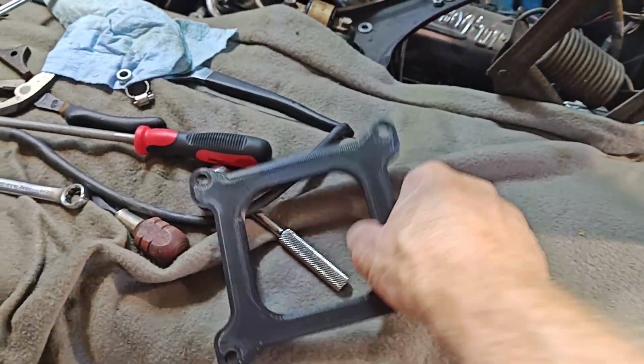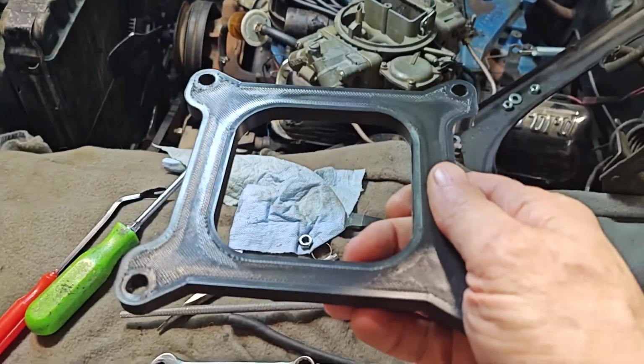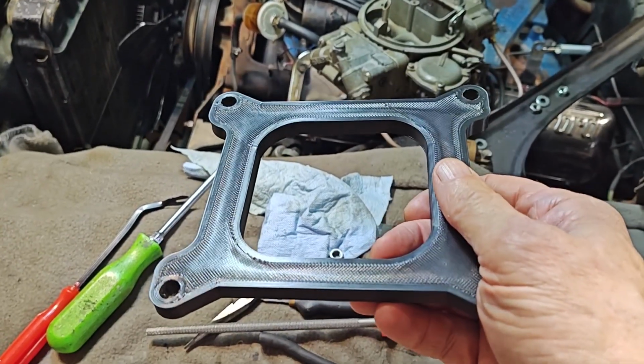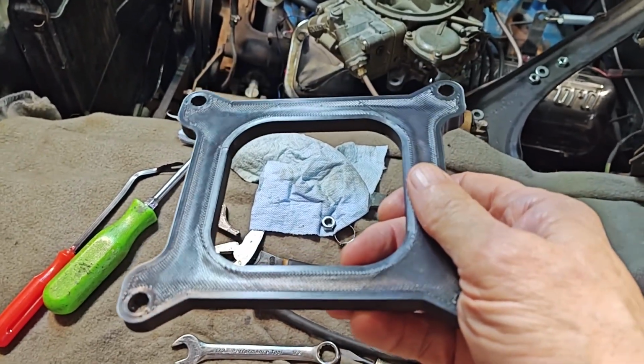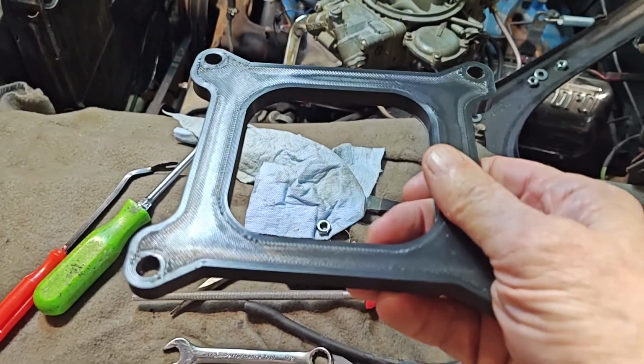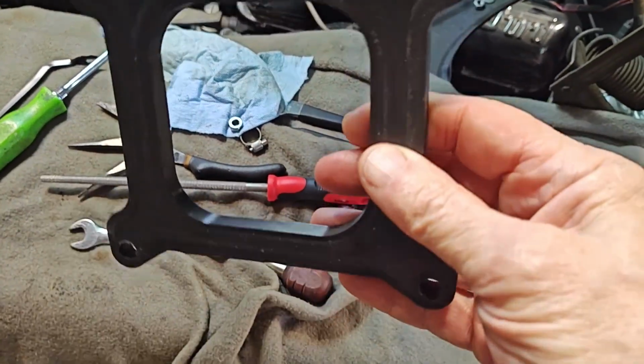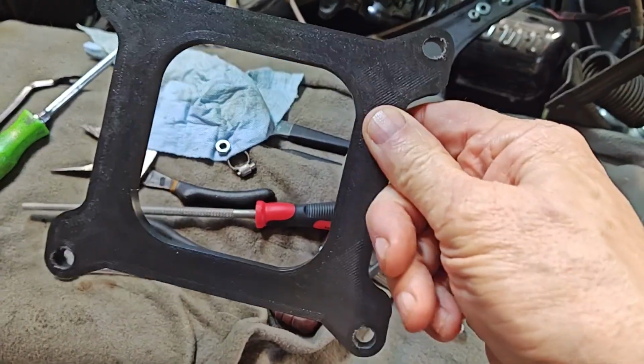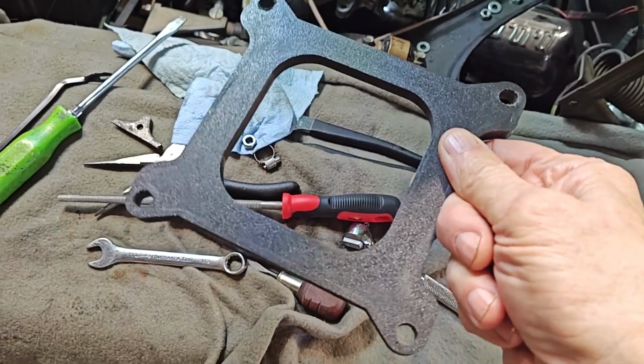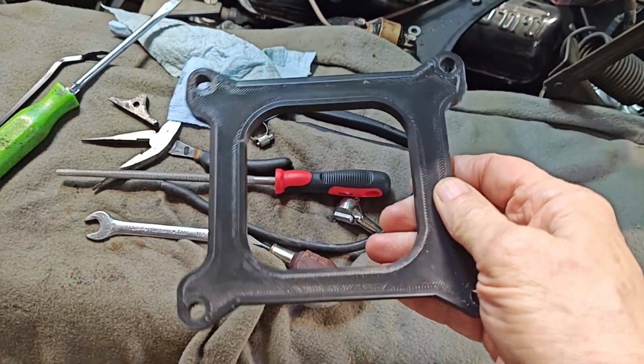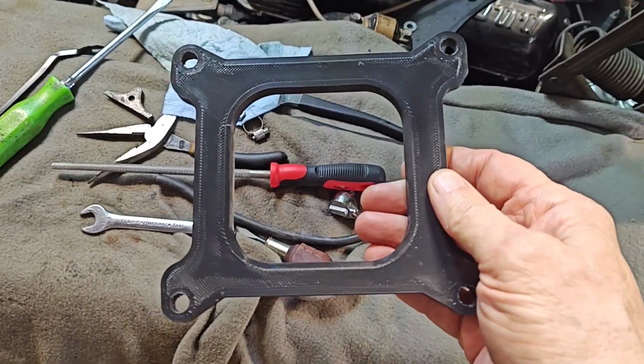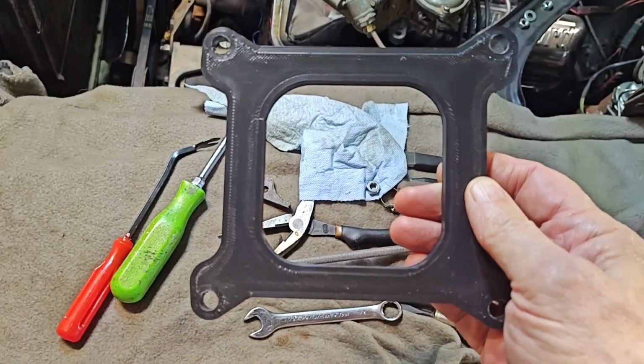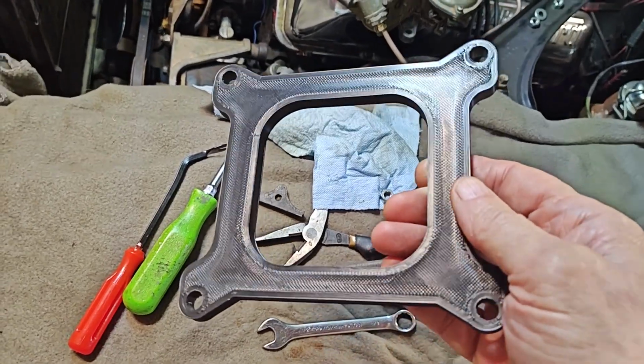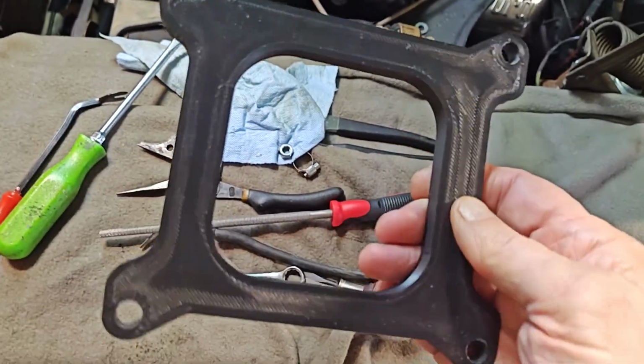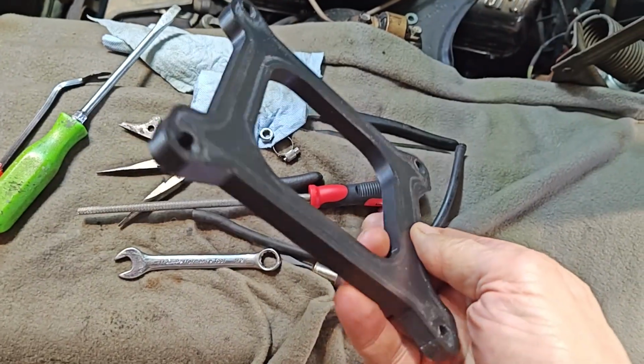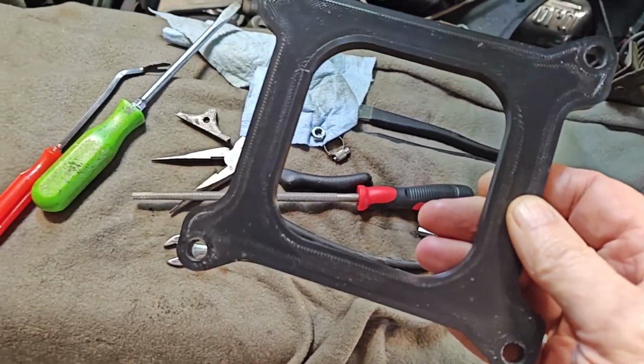So here is my final printed part. I annealed it for about 4.5 hours at 200 degrees Fahrenheit, which is, what is that, 95, 97 C, something like that, I don't know. As you can see, it turned out pretty darn nice. That is the bed side, that is the top side. There was no warping at all, even despite the fact that I forgot the brim, which is kind of annoying, but still no warpage at all.